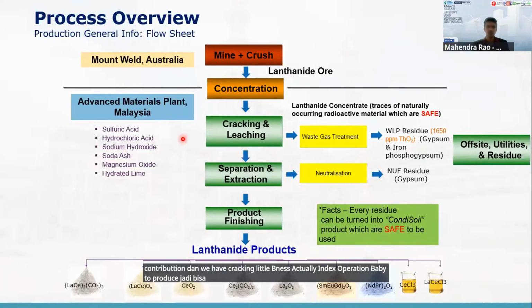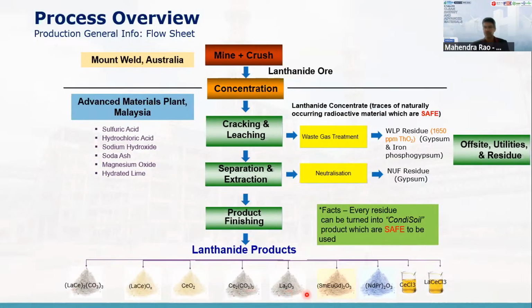So this is a summary of the flow as I showed before. This is the range of materials that Lynas produces: lanthanum, cerium carbonate, lanthanum and cerium oxide, samarium, europium, gadolinium oxide, the mixed NdPr, cerium chloride, and currently we also have the heavy rare earths, Tb and Dy oxides, starting from this April. We already produce heavy rare earths and already have commercialization for those two heavy rare earths. So that is some value added to the Lynas business.